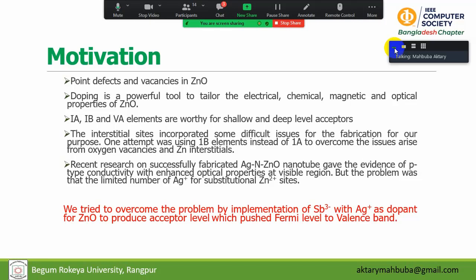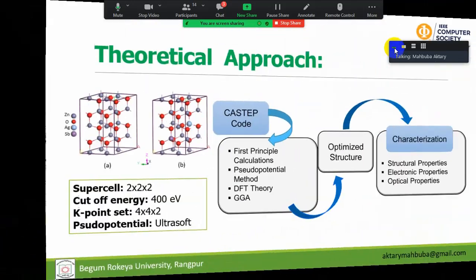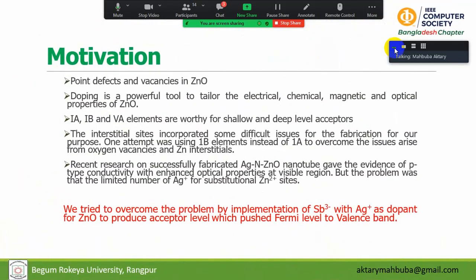Here you can see that I mentioned p-type conductivity, and p-type conductivity is rarely found in the research sector, and we have great concern about getting and designing p-type conductive elements. And here we try to overcome the problem of rare and unstable p-type conductivity by implementation of antimony with silver dopant for zinc oxide to produce an acceptor level which pushes the Fermi level to the valence band.